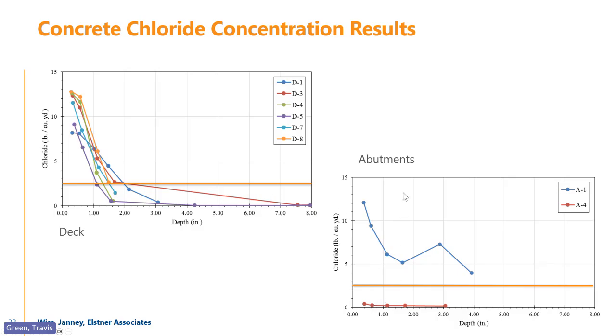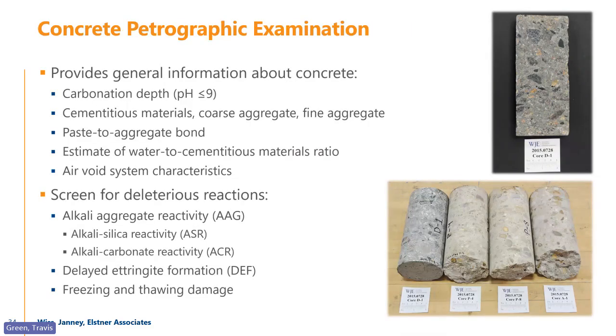And then on the abutments, what you see is abutment 1 and abutment 4 being very different, right? And this is likely due to exposure. This might have been underneath an expansion joint, and this was more protected because we did a couple different zones. But for the deck, we would curve fit this data, potentially into one curve, which gives us the mean and the standard deviation, so that we can use that as a normal distribution curve in the Monte Carlo approach of the service life modeling, right?